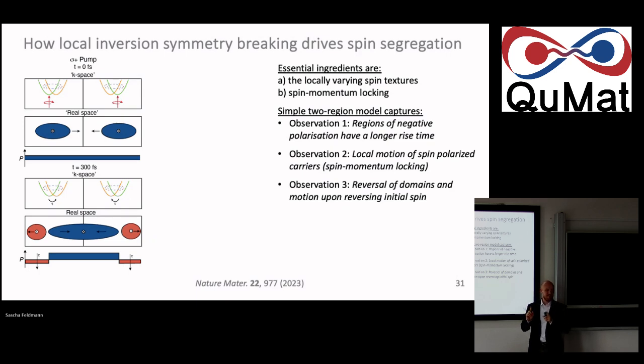But what that now means is, of course, that in the left grain, where I have a certain spin texture, this might mean the spin moves to the right, whereas in the right grain, where I have another spin texture, it might move now to the left, as the local rule of the game dictates by spin momentum locking. Okay, so what now happens if I wait a little time is a spin scattering event will occur. And what happens then? Once I wait, say 250 femtoseconds, I spin flip into the other subband. And what that now means, of course, is that my rule of the game has changed. So if I was spin up and now spin down, I will also now want to flow into the other direction. So you therefore start to segregate out here and change directionality.